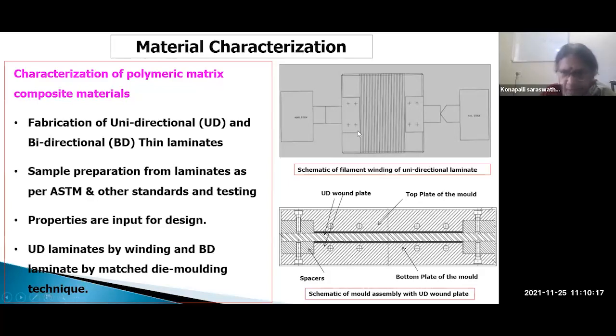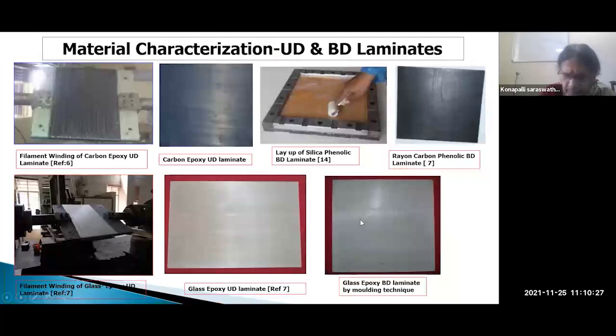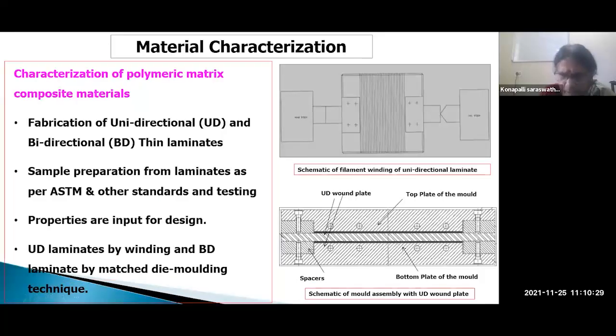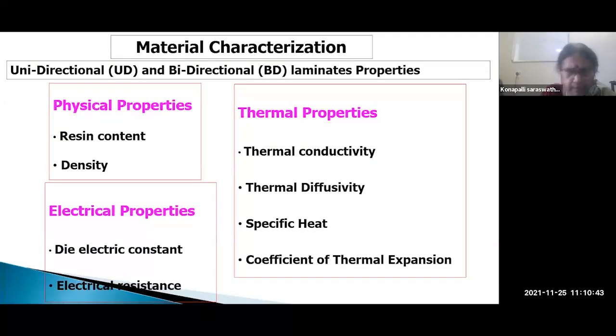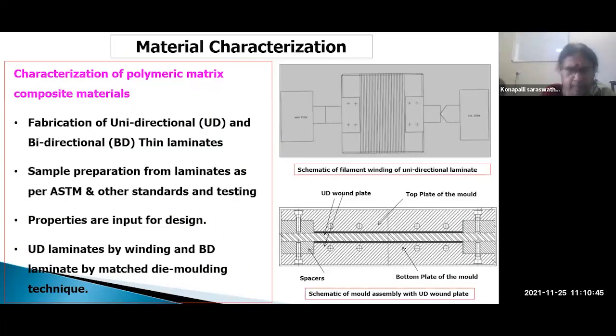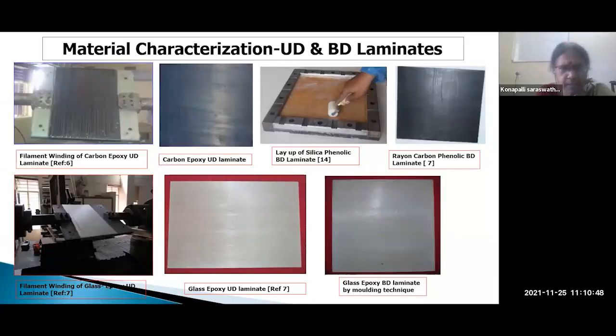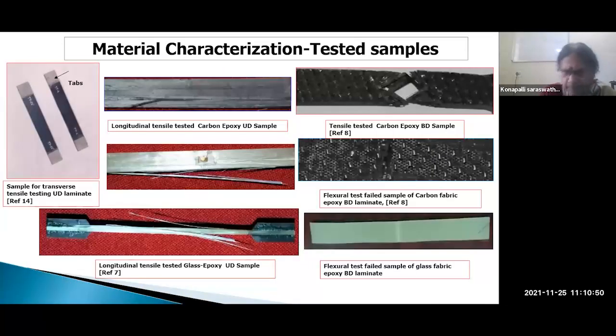So in one winding, you can see this unidirectional, this is schematic. We'll deposit the fibers in this direction, held the plate. After winding both sides of the plate, this is the winding, and then it will be kept in the mold, top and bottom plate. Then it will be cured in hydraulic press under heat and pressure. That was the schematic, and this is actual.